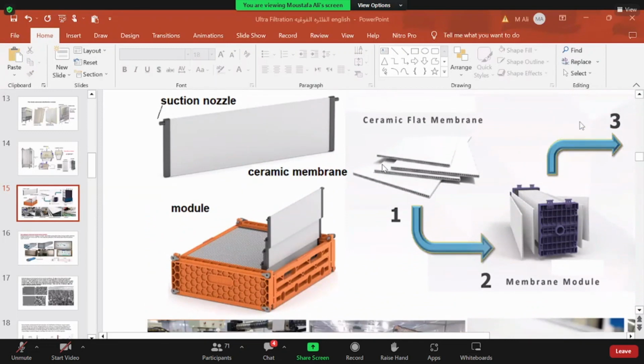To put this membrane inside a module, this can happen by gluing two plastic parts. This plastic part is made from a special material called Noryl, or polyphenylene oxide. That is the name of the material. The two caps, each one has a channel way to collect all the filtrate or water from all these holes or channels to one main channel, then through these nozzles from both sides, left and right, where suction takes place. So it has a suction nozzle either from one side or from both sides, which is more efficient.